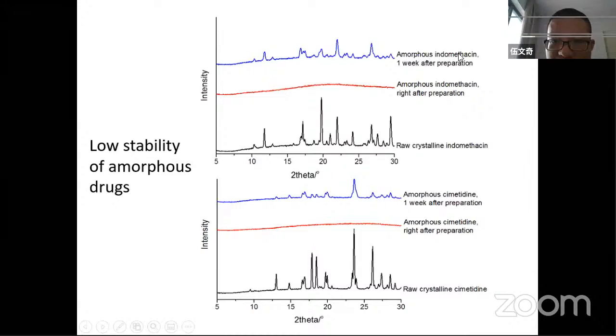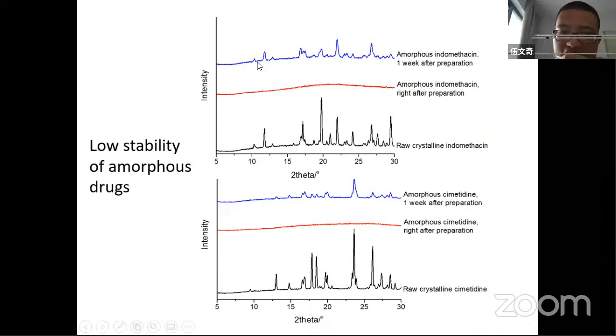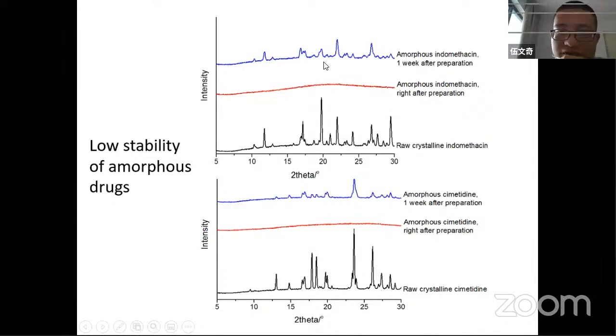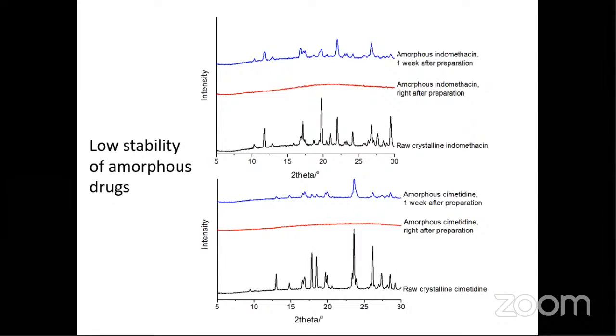But the amorphous indomethacin stored at room temperature, just room temperature, not very high temperature, 1 week later you can see recrystallization peaks already showing. So in this case, 1 week is a very short time—it's not possible, not allowed, just for this sample. Only 1 week of stability is totally not enough.